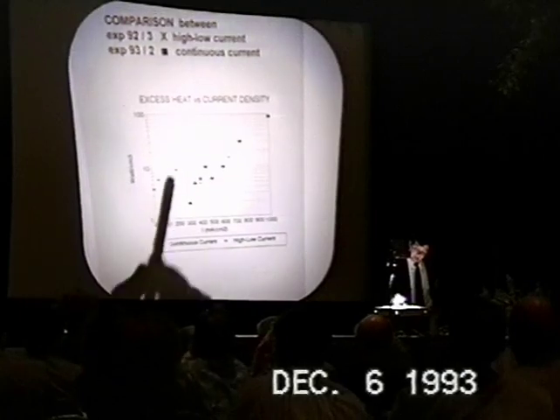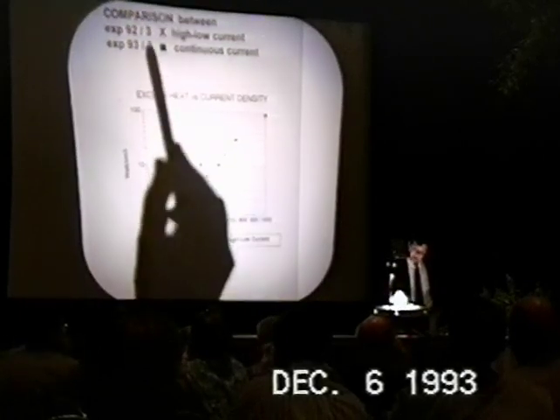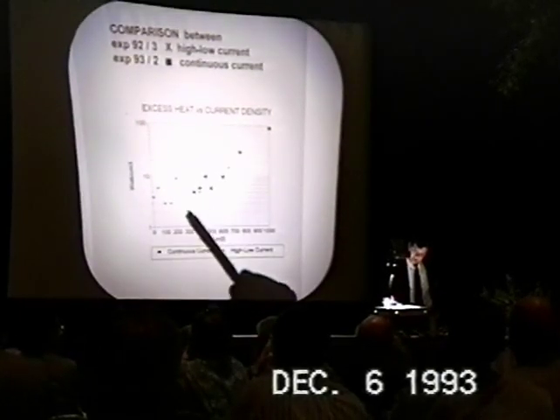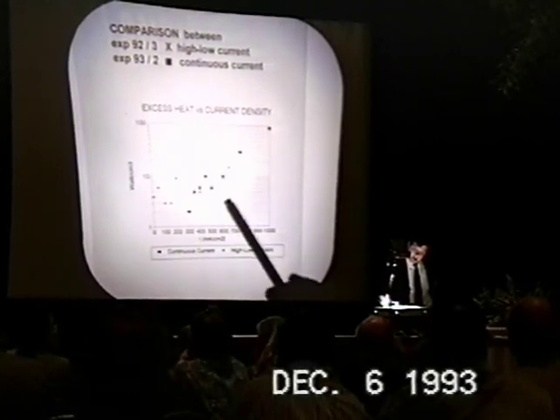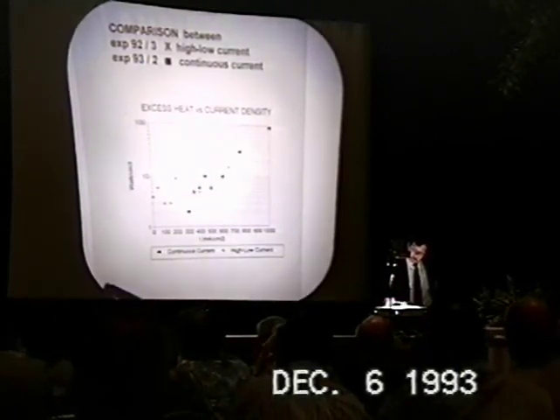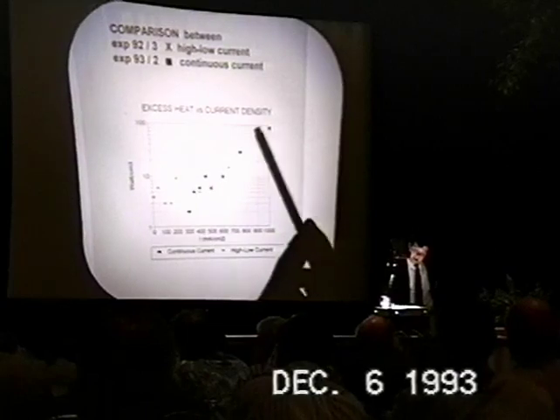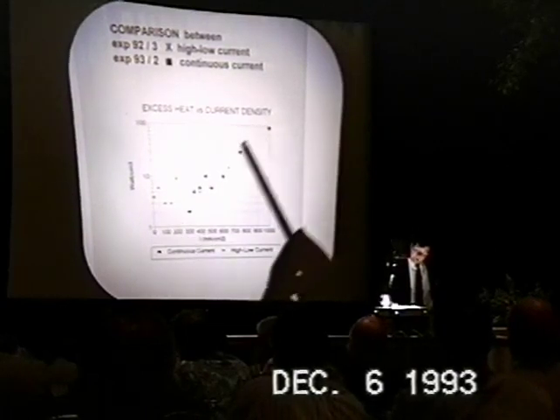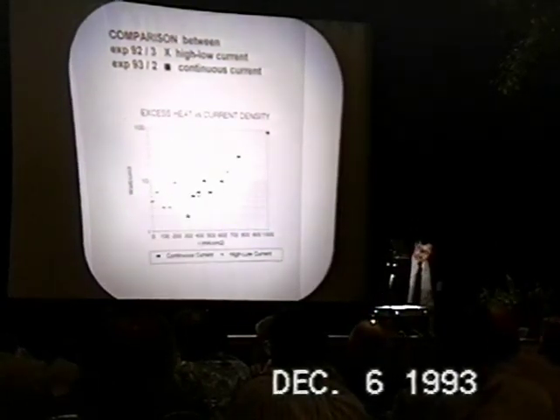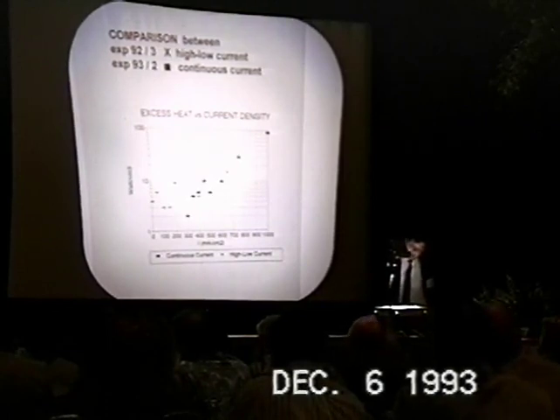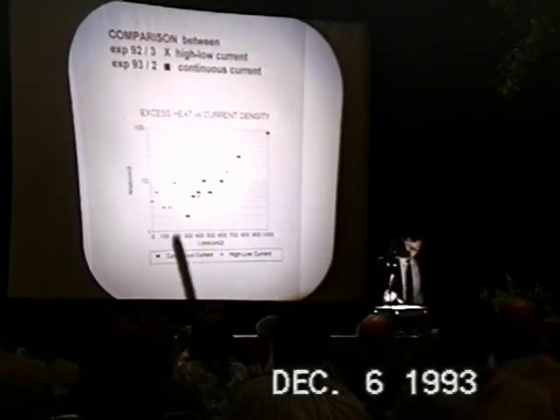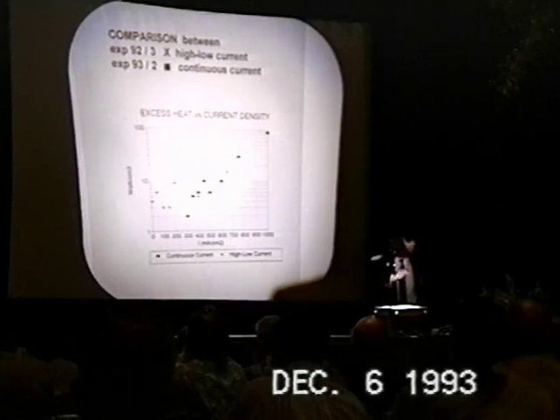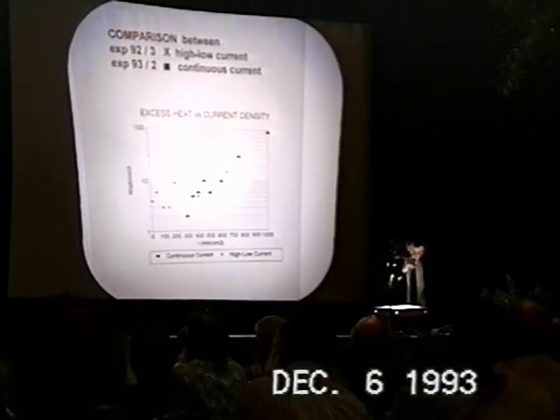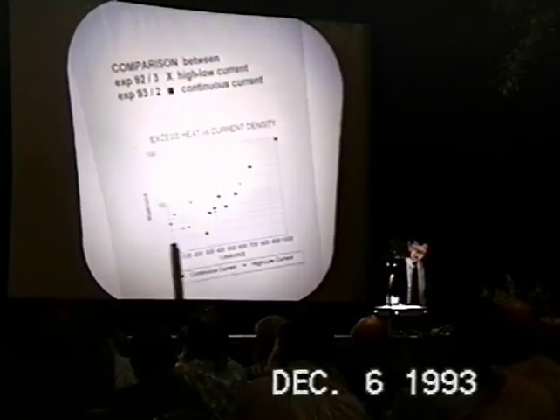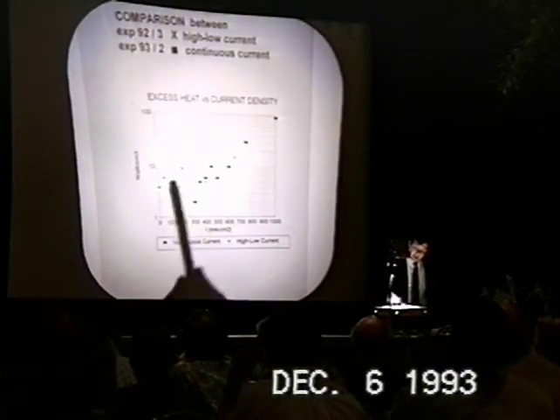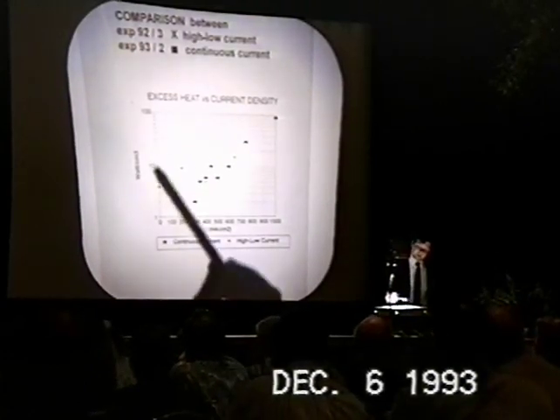The X here is plotted, and the black points are those with continuous current. As you can see, there is a relationship. We observe a relationship with the current, and it turns out to fit very well also with the data from Professor Watson. We don't understand very well why, at a very low current density, there is a big difference.